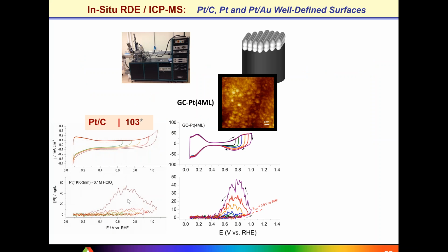So in addition to the ability to control size, we cannot do too much to control the active electrochemical surface area, because sometimes those particles detach, and the most ideal case is actually to work with extended surfaces. We already showed in the past the best way to do that would be to employ thin films. And here you're looking one-on-one at the behavior of a platinum carbon state-of-the-art catalyst with a thin film, which was obtained by sputtering. And they behave pretty much the same.